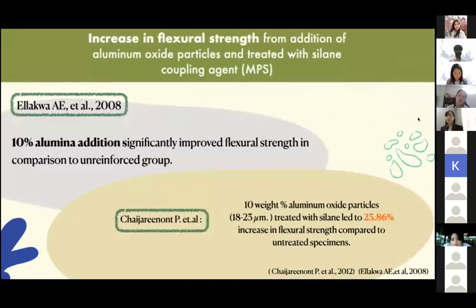Similar to a study conducted by Ellakwa in 2008, the addition of 10% alumina significantly improved the flexural strength in comparison to the unreinforced group, and the study by Chaijareenont in 2012 also states that 10% weight alumina oxide particles treated with silane led to a 23.86% increase in flexural strength compared to untreated specimens.